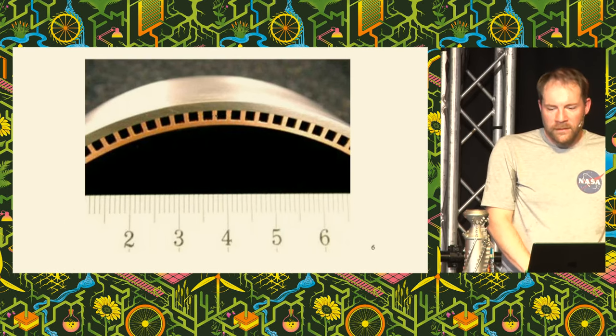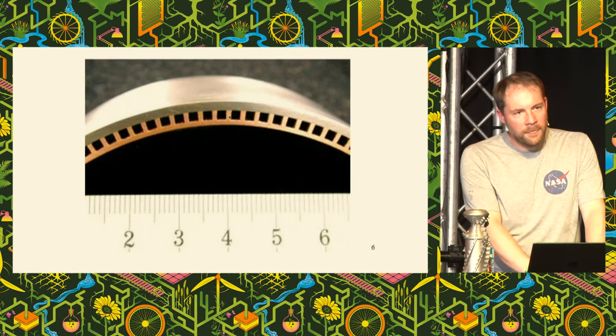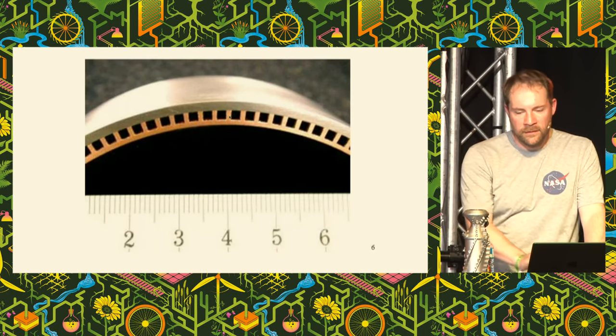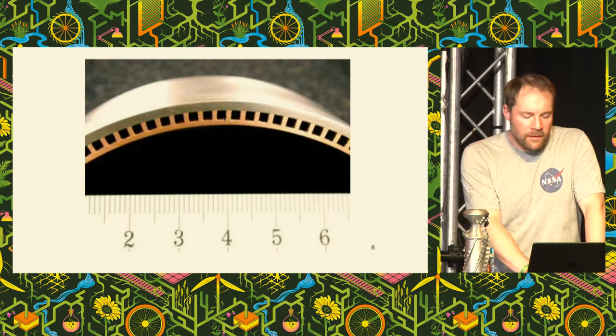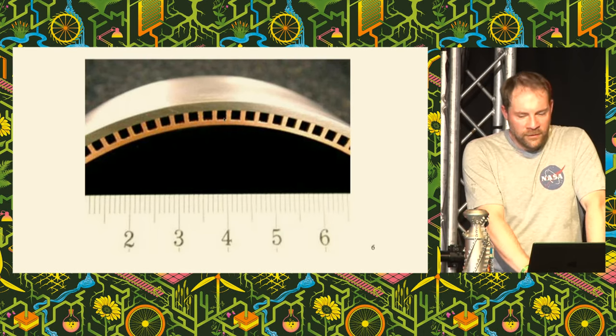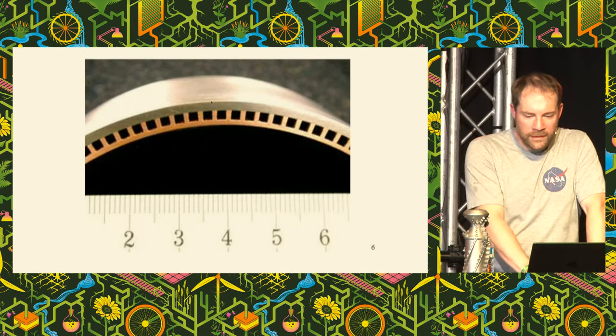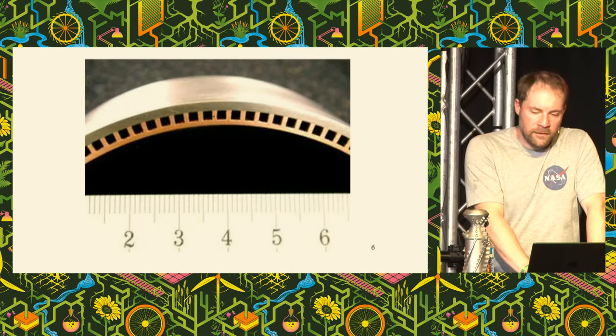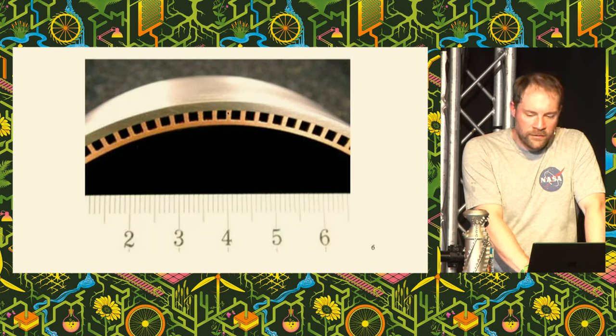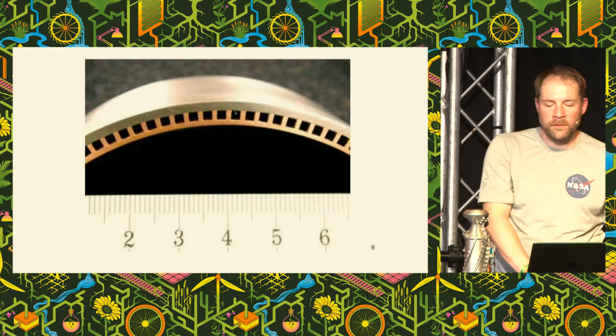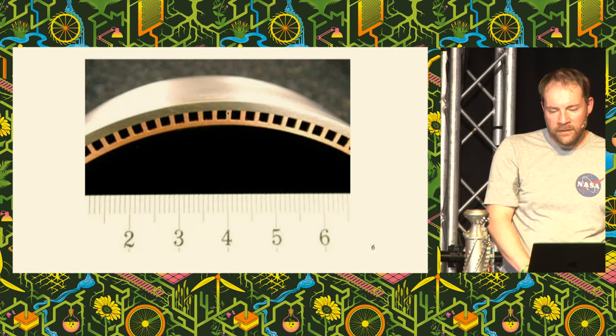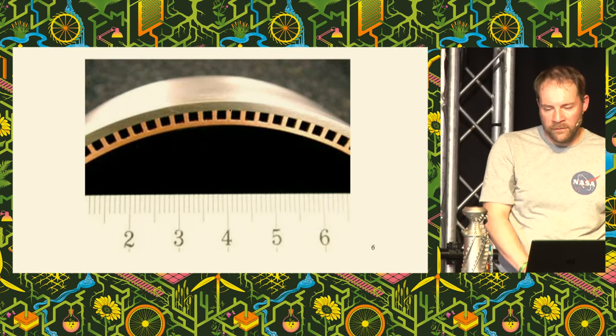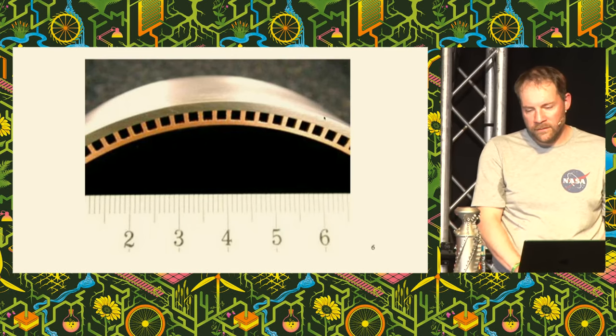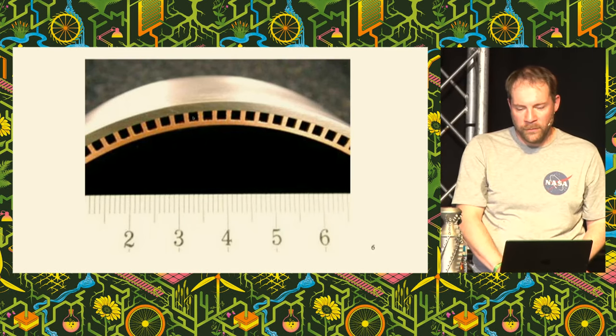Then you fill all of these freshly machined channels with wax and polish them down smooth to be at the same height as the copper fins. And then you burnish conductive silver powder onto the top of the whole thing. And then you can connect it up to electrodes and sink it into an electroplating bath to make it nickel-plated, and over several weeks, up to months, grow layers of nickel on the outside to give yourself a reinforcing jacket to support the weight of the copper.